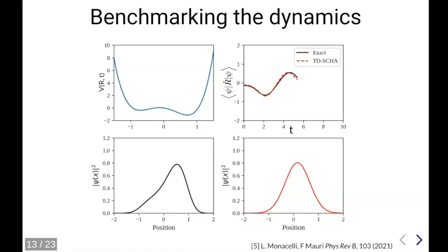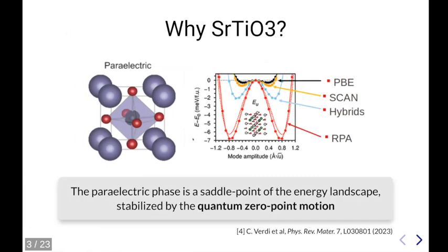So the one that I showed you in the previous slide, this one here, is a really big magnification. You can see it's only 7 millielectron volts per formula unit, so it's not actually that much of a double well. What you see is that the zero-point energy is much above this barrier, and therefore your wave function will differ from the Gaussian, with a deformation with respect to the Gaussian, but it will still be a single-peaked function, and so the Gaussian remains a good approximation for it.